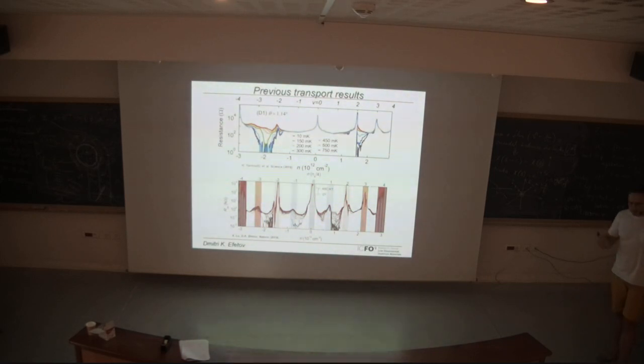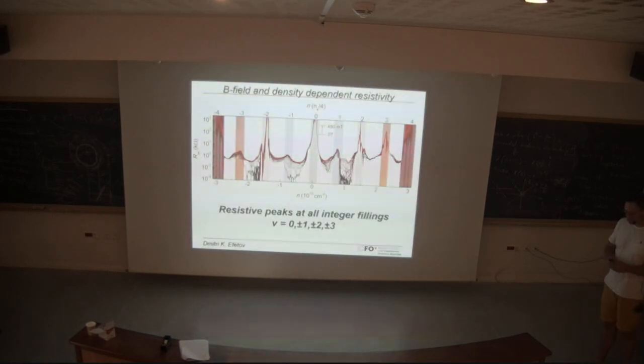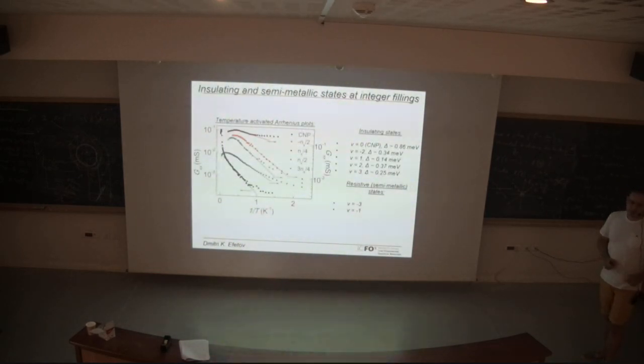But as you can see, there are also other features arising, also at integer fillings. We see a clear resistance increase here at -3, a clear resistance increase at -1, which is completely missing in this work. And then the same thing happens at +1 and +3. So what it seems is happening is that we observe new correlated states, which now correspond not only to fillings of 2 and -2, but also to all of the integer fillings of the moire lattice. At all of the filling factors, we observe resistive peaks, and similar to the work by Pablo, we can also now try to do temperature activation of these resistance peaks, and extract the gap sizes in these.